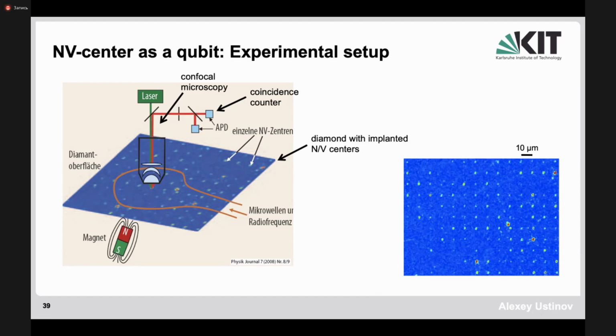The NV center is a single photon source, and it can be detected by using the so-called confocal microscopy. So in this case, you focus the laser beam not only in 2 dimensions, but you also make the focus in 3 dimensions, basically by choosing the focusing at a particular distance from the surface of the crystal, and then changing this focal point along the beam propagation direction. And then the setup involves the green laser, which is high energy, which you use for pumping and initialization of the qubit. This is green laser here, which is coupled here via the beam splitter.